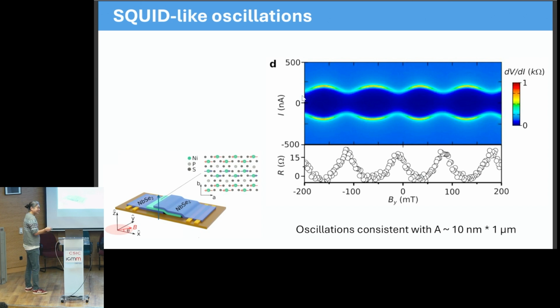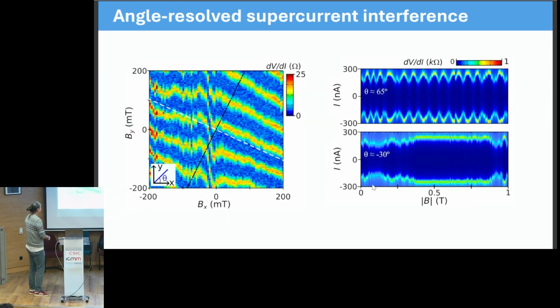Okay? We studied this more carefully, because then we thought, okay, we have some kind of localized channels here, and of course we think, could this be topological, etc. Now, since our experimental setup allows, we have a vector magnetic field, so we can actually rotate this magnetic field over the plane of the junction. So here it's applied over a certain direction, but we could apply it by varying and trying to scan where these localized states are. And this is the measurement that we did. So this is over the plane of the junction. And we observe that essentially the oscillations follow these parallel diagonal lines.